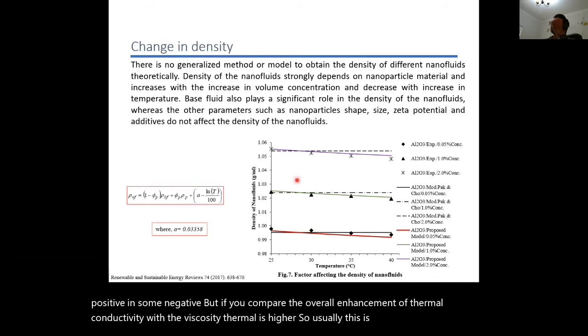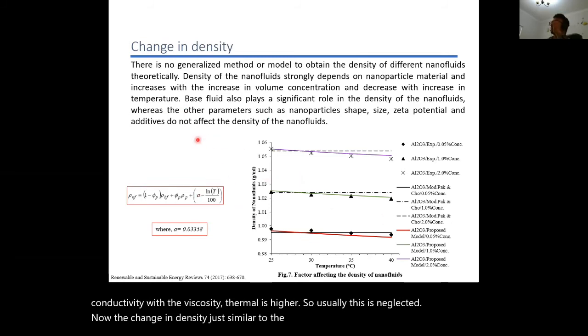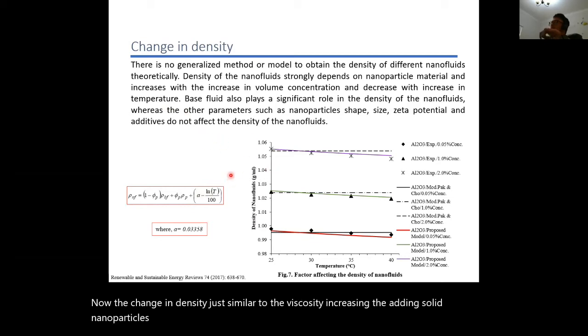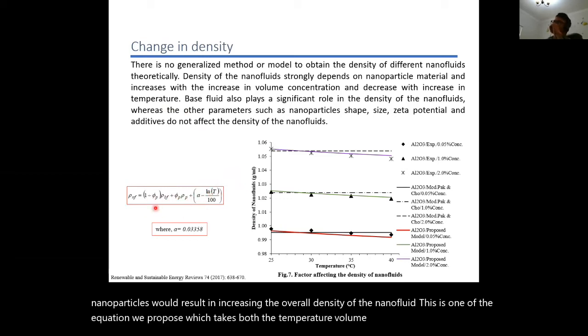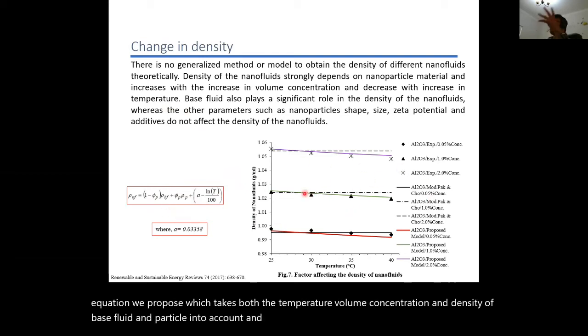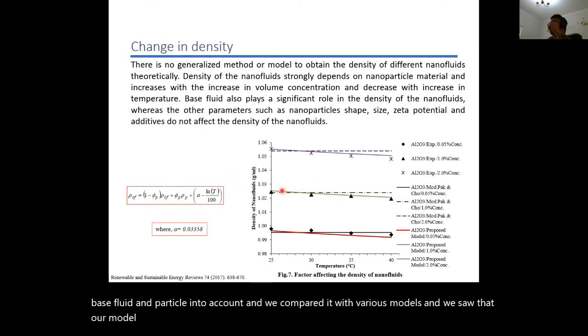Now, the change in density. Just similar to the viscosity, adding solid nanoparticles would result in increasing the overall density of the nanofluid. This is one of the equations we proposed, which takes the temperature, volume concentration, and density of base fluid and particle into account. We compared it with various models, and we saw that our proposed model gives much better results compared to the experimental study versus that of Pak and Cho.